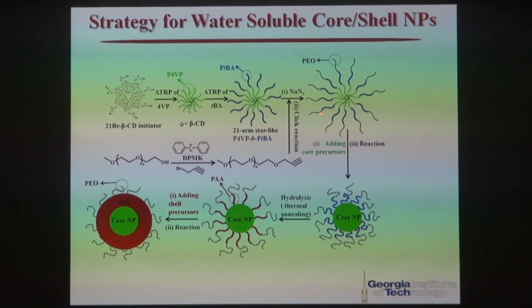Now to make this water-soluble core-shell nanoparticle, we have to make this star-like tri-block copolymer. To make this, we combine two-step atom transfer radical polymerization with a one-step click reaction. First of all, we made the 21-arm star-like poly(4-vinylpyridine)-block-poly(tert-butyl acrylate) by sequential atom transfer radical polymerization of 4-vinylpyridine and tert-butyl acrylate. On the other hand, we prepare propargyl, triple bond terminated polyethylene oxide. Then you do the click reaction between this triple bond terminated PEO and the azide functionalized star-like P4VP-block-PTBA, ending up with this star-like tri-block copolymer.